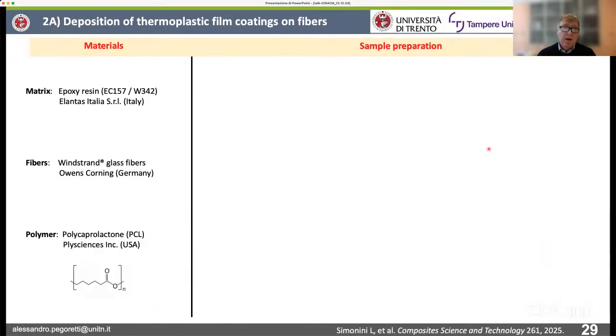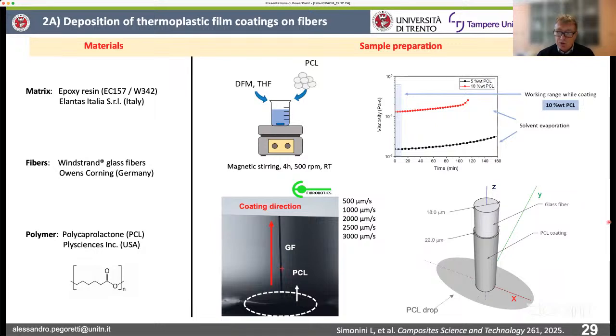Now, we actually decided to investigate by using exactly the same materials, so epoxy, glass fibers, and polycaprolactone, the possibility to reach a continuous coating on the glass fiber by using the same machine I showed you before, of course, by changing the velocity of the fiber to move into the liquid resin. It is possible to deposit a continuous coating of polycaprolactone on the surface of the fibers.